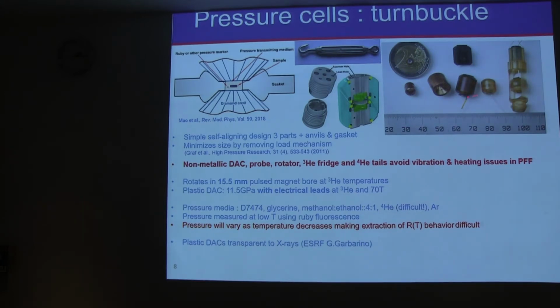There are several designs: metallic ones, one here with a large aperture for optical measurement, and some made out of plastic to do pulsed magnetic field measurements, to avoid any heating or vibration due to the strong gradients in field. We can rotate them at helium-3 temperatures. We can go up to almost 12 GPa with the plastic ones and up to 25 GPa with the metallic ones. We use different pressure media for different purposes, because some pressure media can react with the sample, so we have to be careful about that.